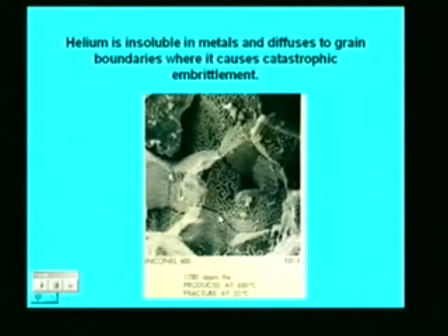Well, helium is insoluble in metals. Talking about why helium is so bad. It's insoluble in the metals and diffuses to grain boundaries where it can cause severe embrittlement. Now, if you look at this fracture surface, remember metals are crystalline. We have fairly fine grains, and you can see from this fracture surface that this material has fractured along the grain boundaries. That's what we call an intergranular fracture.